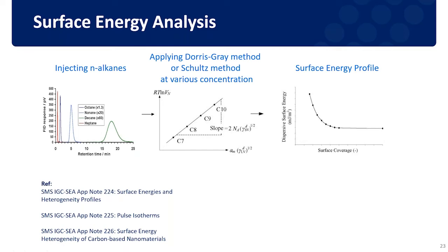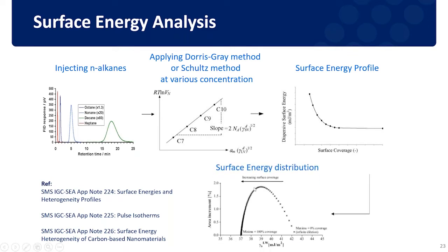And then for a more illustrative interpretation of the data, we can do a point-by-point integration of this surface energy profile to get a distribution with the surface energy on the x-axis. So we have the high energy sites on the right-hand side and the low energy sites, which are the majority on the surface, on the left-hand side. Then we can compare the distributions of different materials to see the heterogeneity of the solid material.